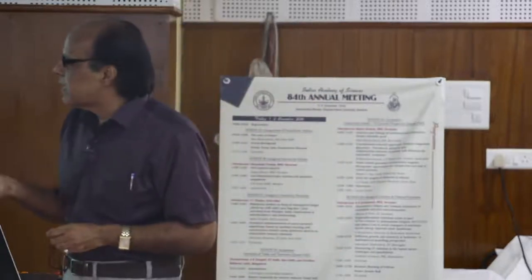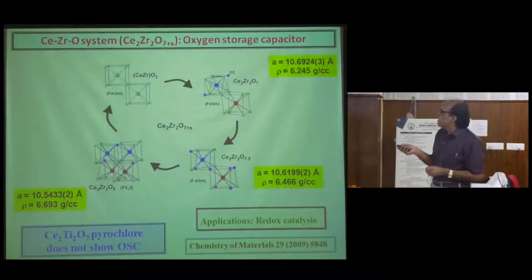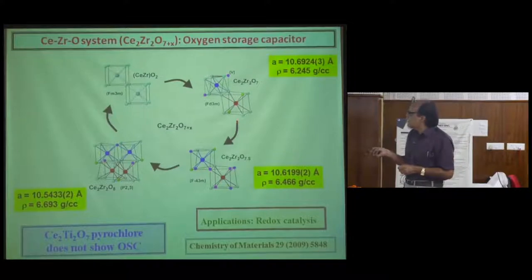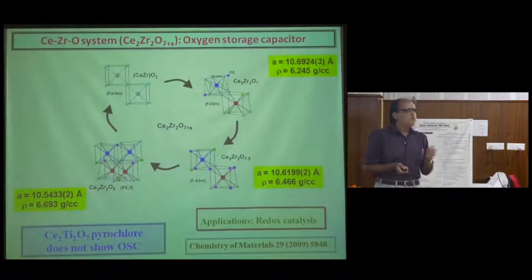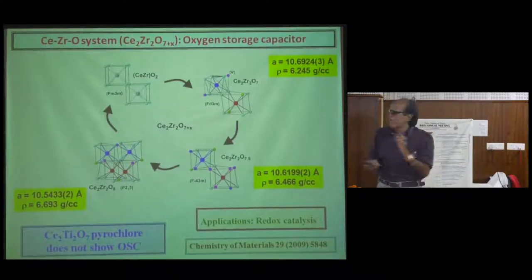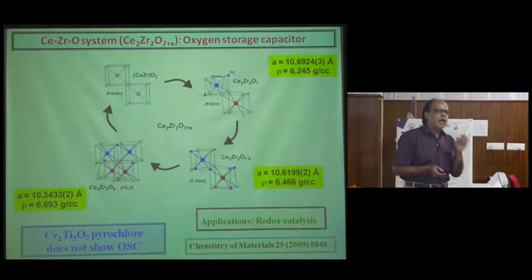The concept behind the design of new oxygen storage materials is that you must have the right combination of cations which can satisfy the coordination number requirements of different structures encountered upon oxygen loading and unloading. These kinds of materials have tremendous applications.